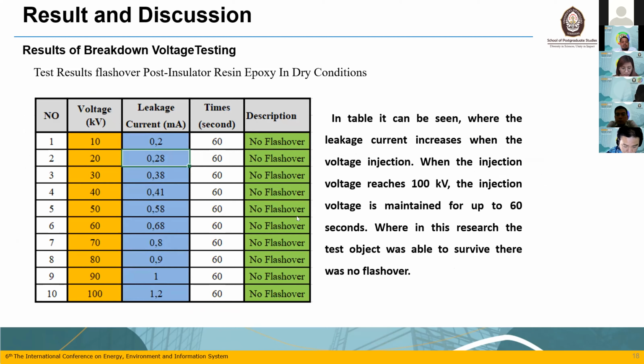Result of breakdown voltage testing, the result of flashover of the post insulator epoxy resin in dry condition. In the table it can be seen that the leakage current increases as the voltage injection increases. When the injection voltage reaches 100 kV, the voltage is maintained for up to 60 seconds. In this result the test object was able to survive, there was no flashover until 100 kV with leakage current 1.2.